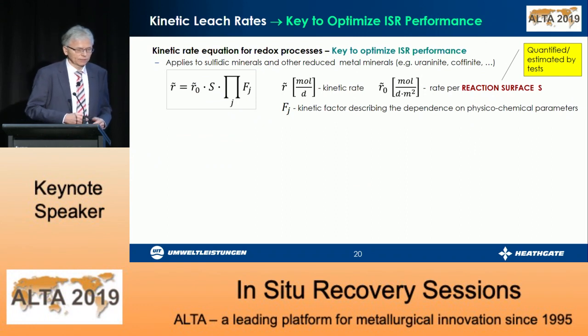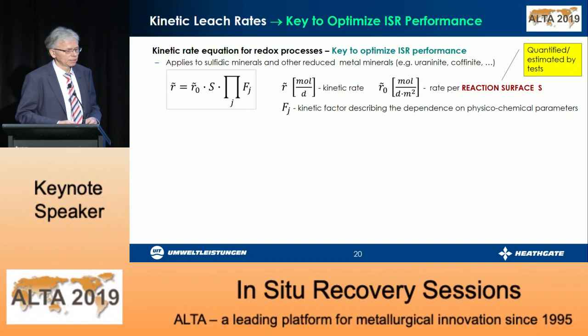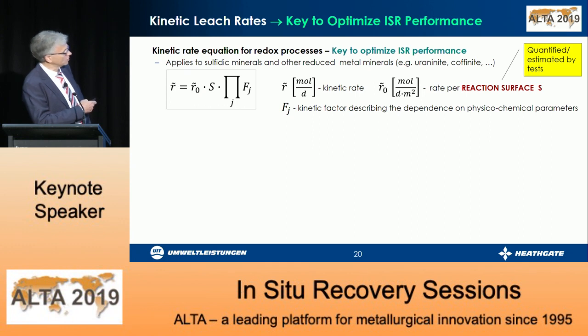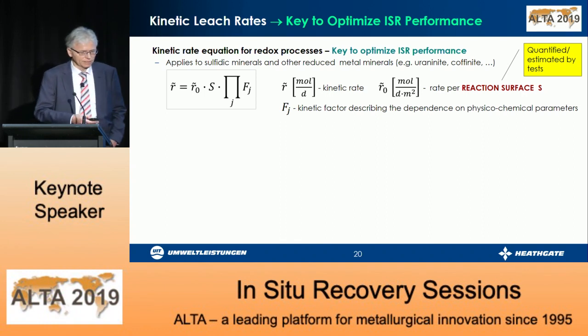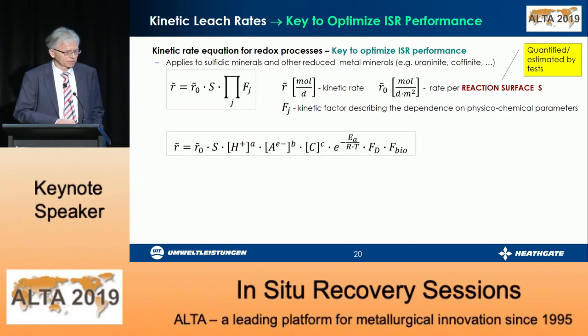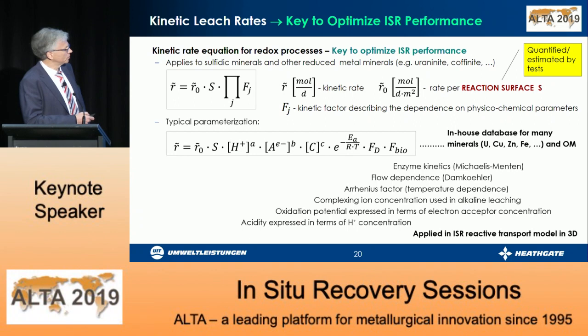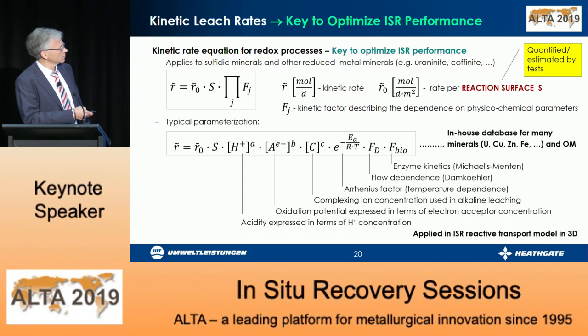Leach kinetics are typically represented by some empirical formula comprising a basic kinetic rate factor, that is the reactive surface I was referring to already, and then we have the product of different kinetic factors describing the dependence on the physico-chemical conditions. Typically, we have to consider quite a few factors or terms in this formula. And here we have the acidity, the oxidation potential expressed in terms of electron acceptor concentration, the complexing ion concentration applied in alkaline leaching operations, the temperature dependence, that's the Arrhenius factor, the flow dependence based on the Damköhler approach, and last but not least, the enzyme kinetics.